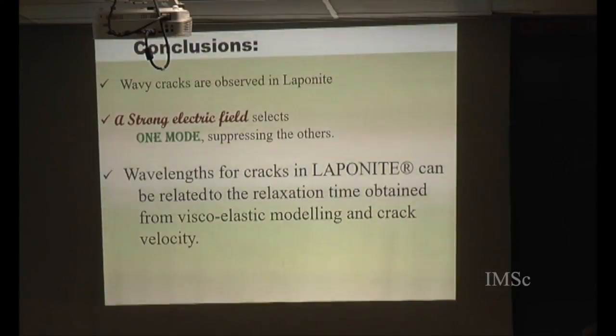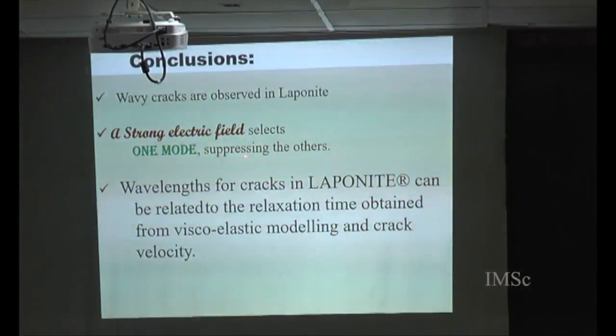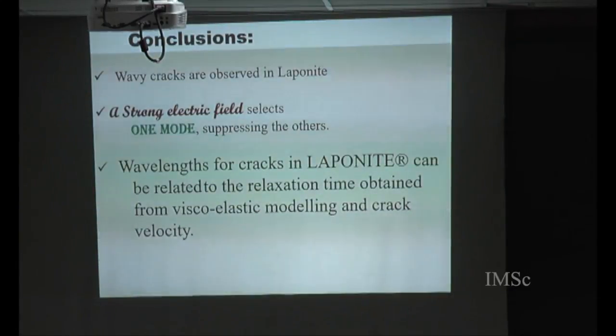So to conclude, I think I'm finishing early. So the conclusions are like this, that in Laponite, we have these wavy cracks, and it seems that when there is a voltage, the wavy nature changes, and for a strong enough electric field, only one wavelength seems to be selected. Whereas for a weaker field, we have a superposition of some different sinusoidal waves. And through this simple reasoning, we can relate the wavelengths for the cracks in Laponite to the relaxation time, which comes from the viscoelastic modeling for the crack velocity.